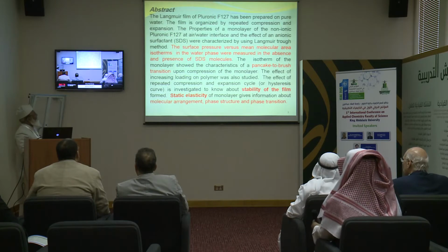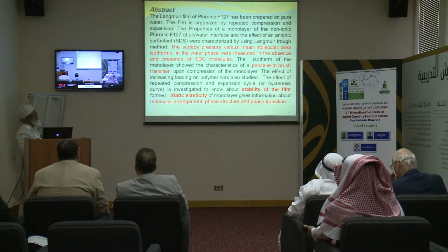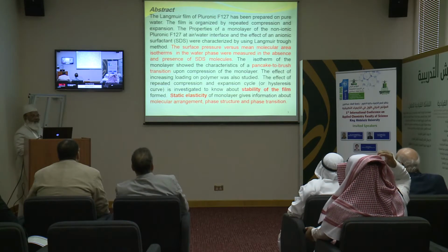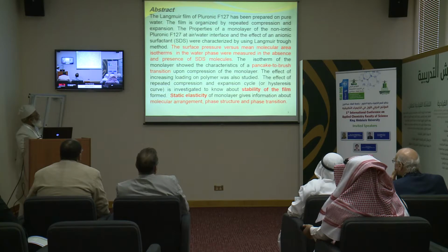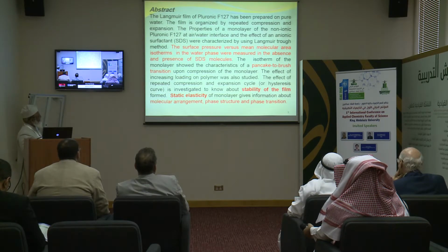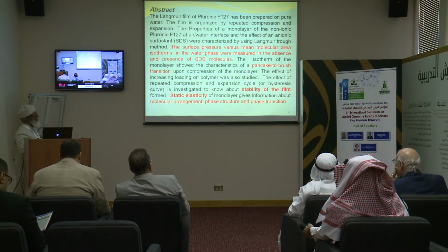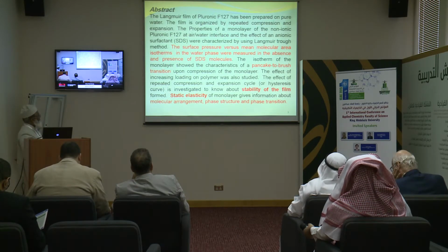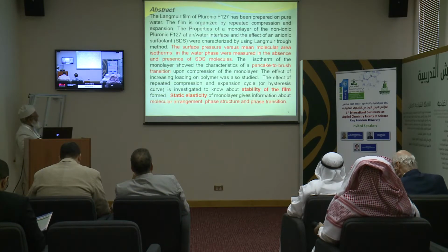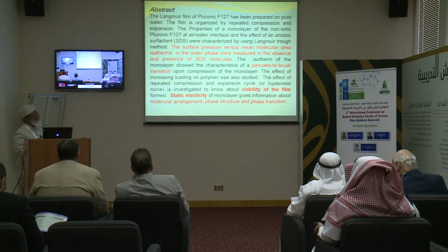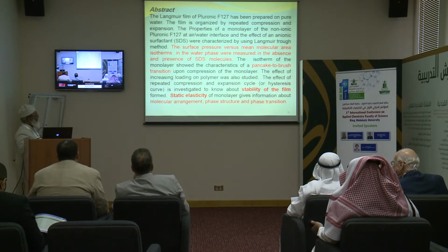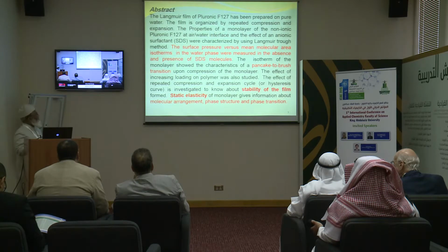The Langmuir film of Pluronic has been prepared on pure water as a subphase. The film has been organized by repeated compression and expansion. The properties of the monolayer of the non-ionic copolymer Pluronic at the air-water interface, and the effect of the anionic surfactant sodium dodecyl sulfate, were characterized using the Langmuir-Blodgett method. The surface pressure versus mean molecular area isotherms in the water phase were measured in the absence and presence of SDS molecules. The isotherms of the monolayer showed the characteristics of the pancake to brush transition upon compression of the monolayer. The effect of increasing loading of the polymer was also studied.